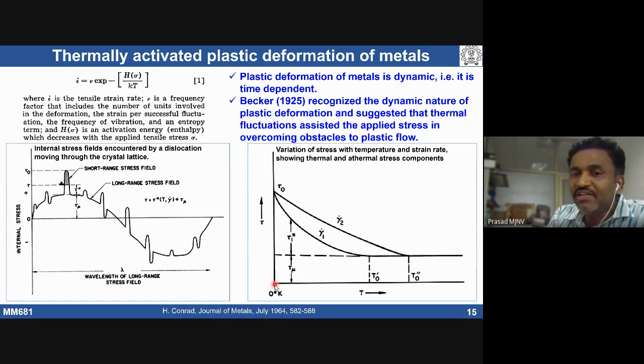So this is the stress required now at 0 Kelvin, where there is no temperature. Here I have taken two different strain rates, gamma 1 dot and gamma 2 dot, these two different strain rates, increasing strain rates. So at 0 Kelvin, I need to apply a tau naught stress.